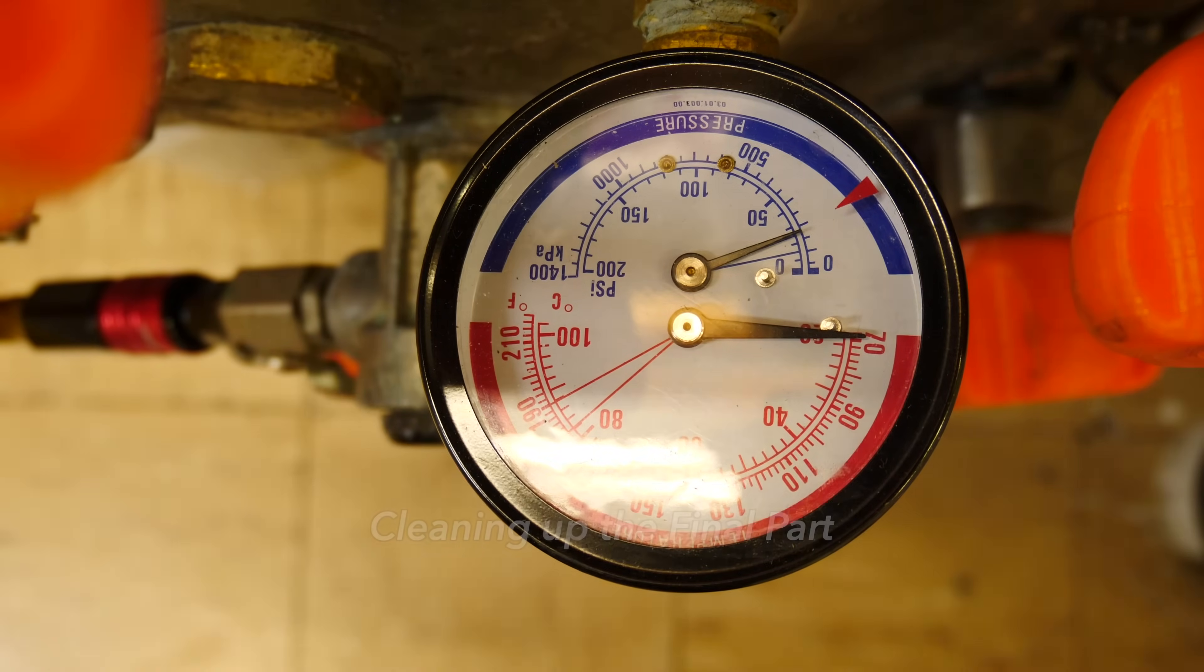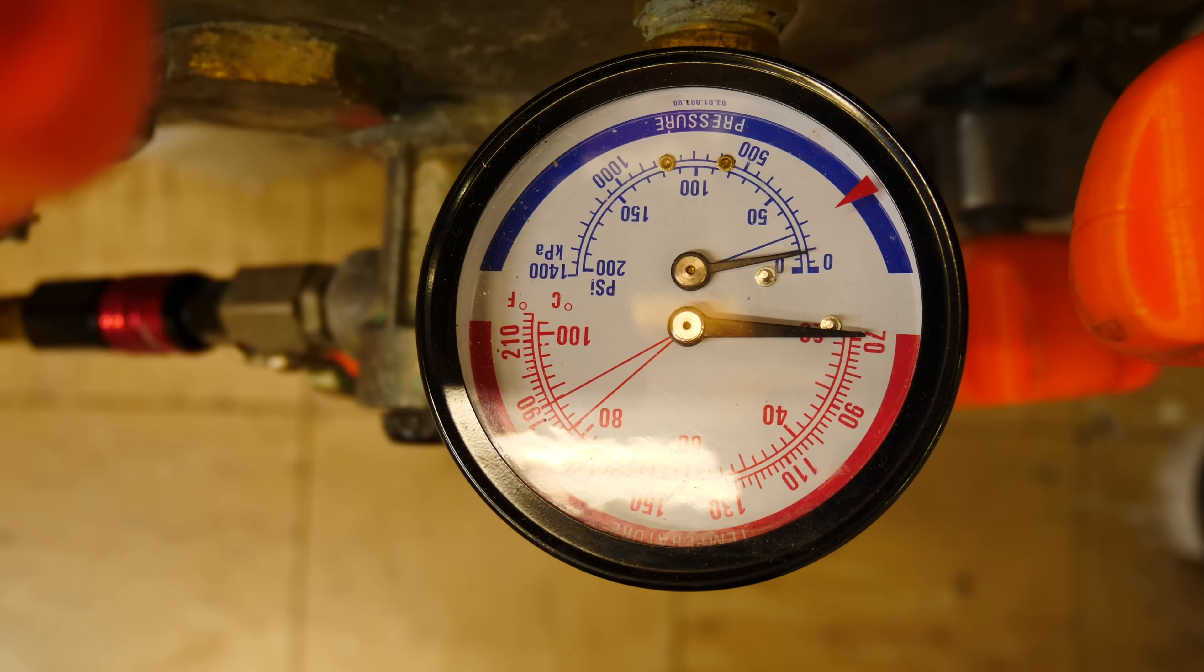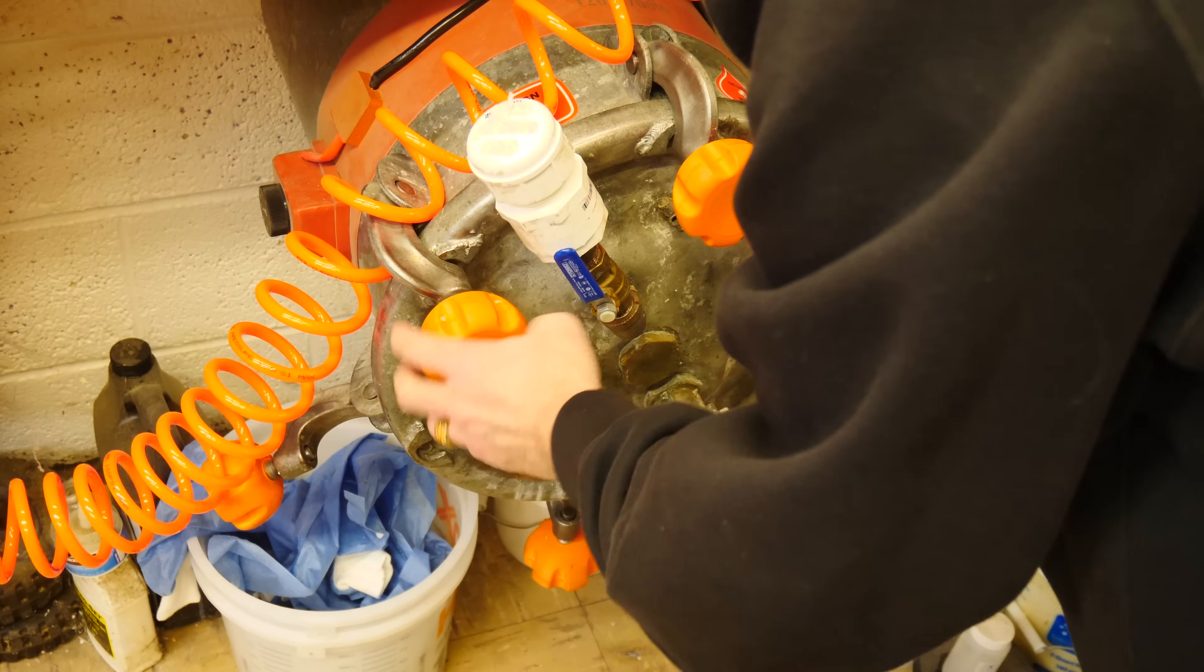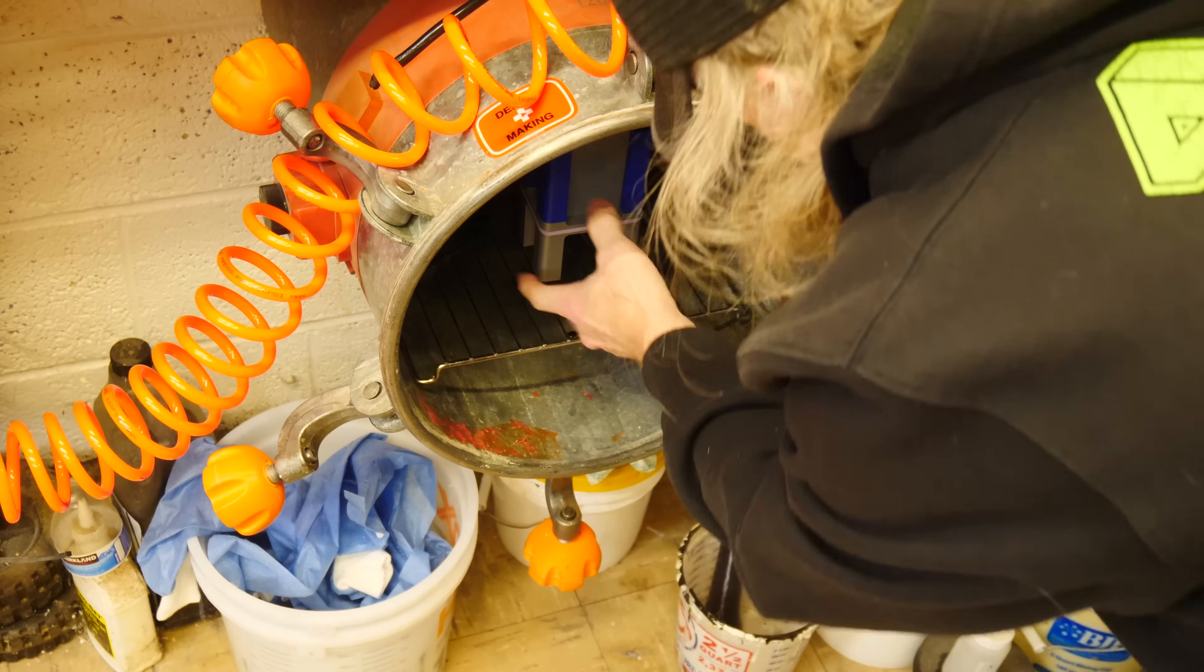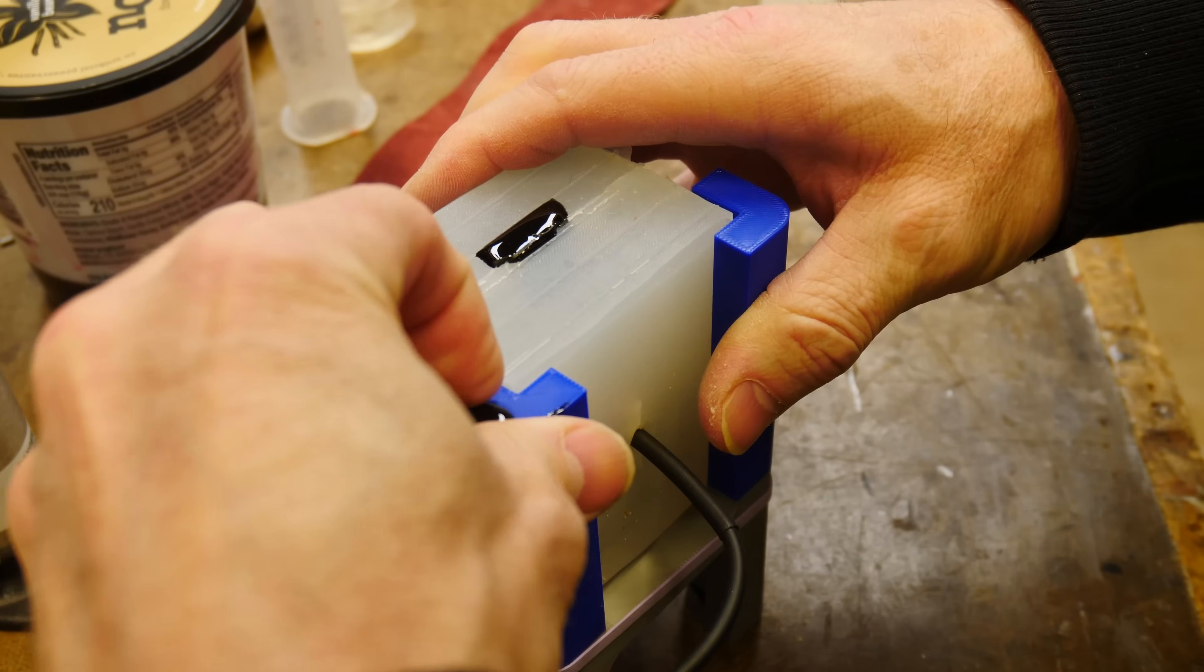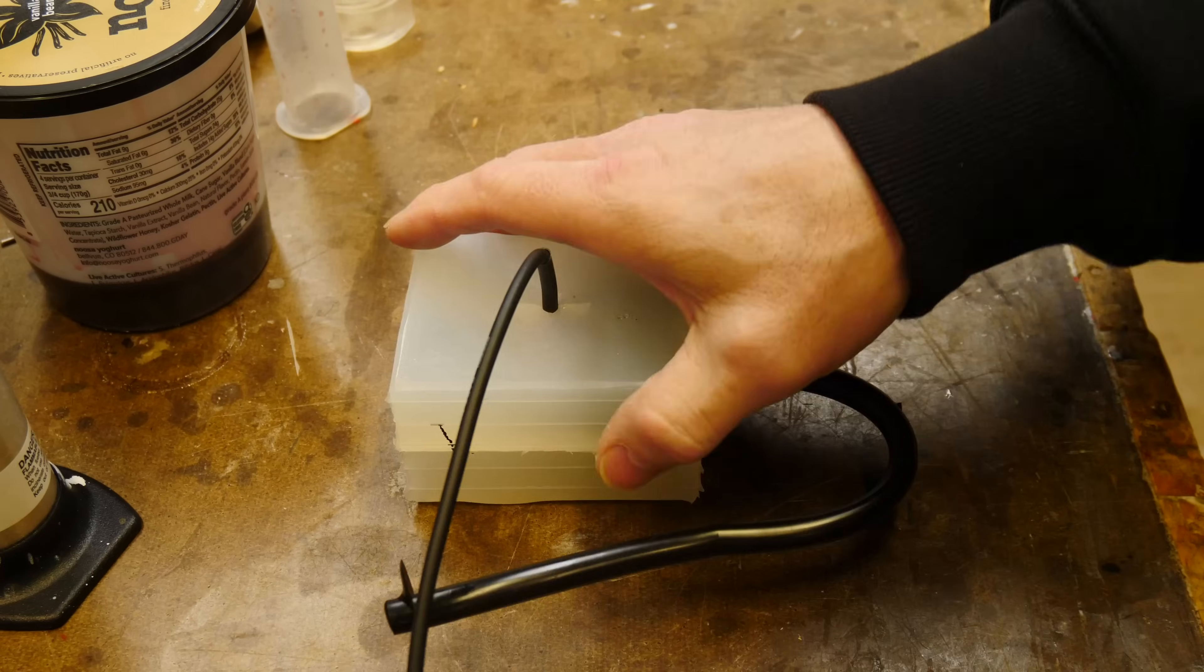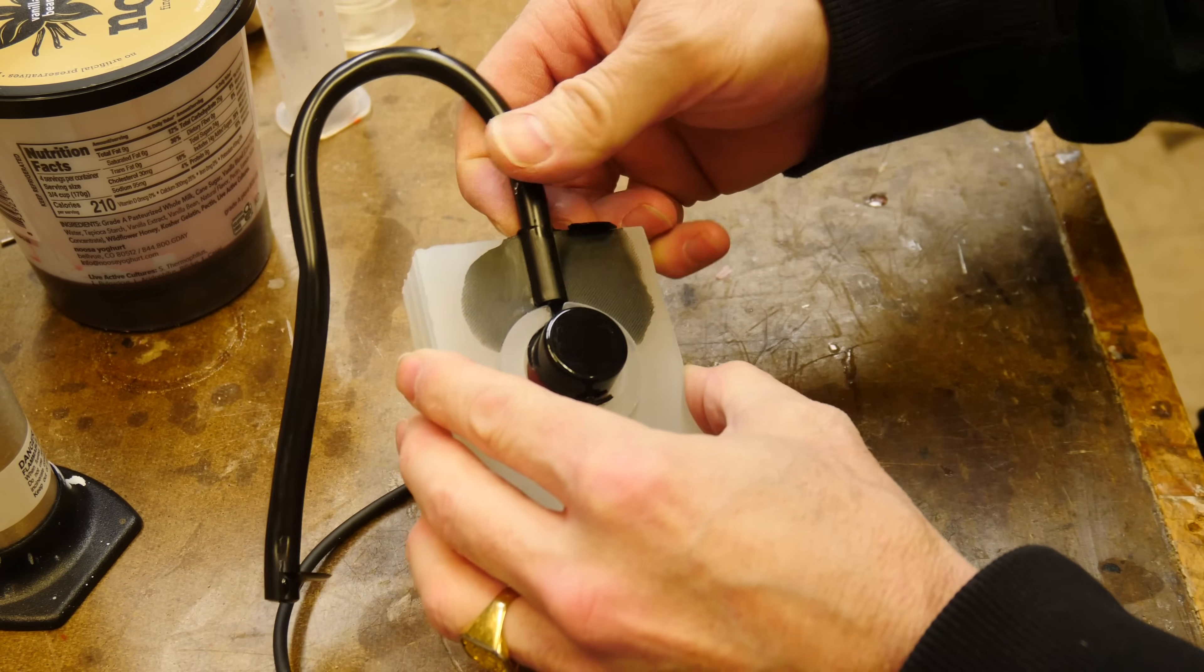Because the resin is soft and not as hard as like a 70D, we don't need a lot of pressure, so if there are bubbles, we don't want them expanding back out in the part. The main reason for going in the pressure tank is the heat because it's heated, and it helps me cure the resin. Let's demold and check out the part. We can pull the tube up from the bottom and take the mold apart, and there is our part.